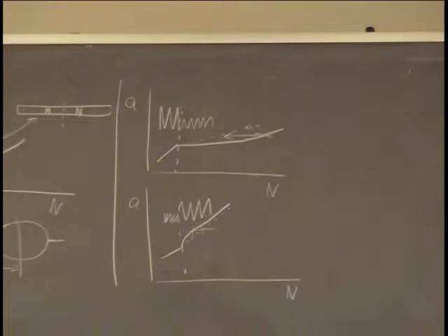And in the past, when we didn't know about the mechanisms, we just added, so to speak, the damage caused by the various load cycles in a linear manner, which is obviously not correct. But fortunately, in most cases, if we would do what we call a linear damage accumulation, we would in most cases be on the safe side. Not always, but in most cases.